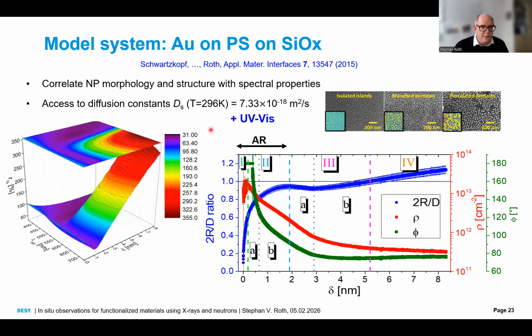And then you see, for example, that for very low depositions here, 0 to 2 nanometers, you have an anti-reflective coating due to the existing plasmon resonance. And only when you continue above these 2 nanometers, when more and more gold comes on, the reflectance goes up and up and up, as you would typically expect for a gold layer. And this region here can be used for SERS effects. Good.